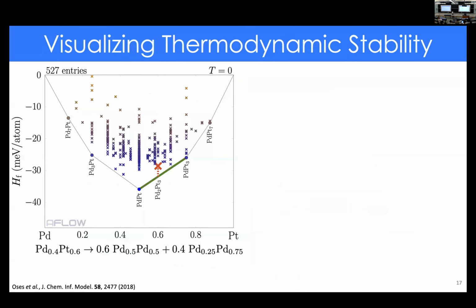Let's go back to this picture. Obviously not all of the points are shown to define the hull here. All of the points that are off the hull are unstable. Effectively, if I try to make this composition, it's going to decompose into this linear set. You just drop your line directly down and look at what the facet is below it. So we can define this decomposition reaction. If I try to make that composition, I expect it's going to phase separate into this reaction. And I can even quantify the energy of that reaction. Very simply, it's just the distance on this picture.